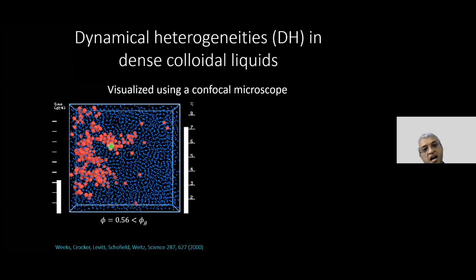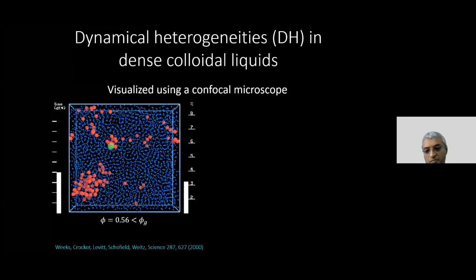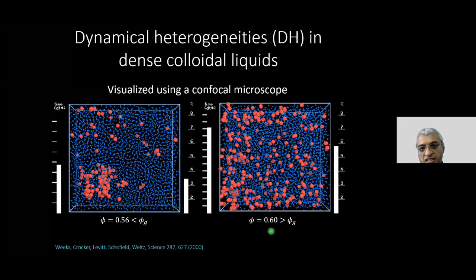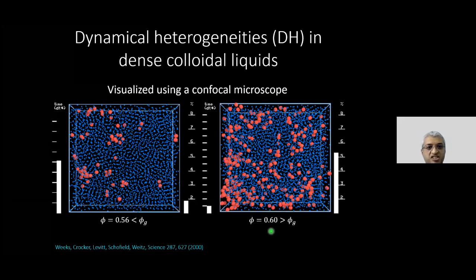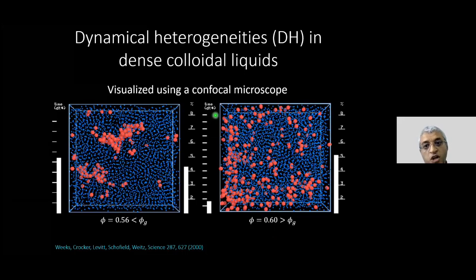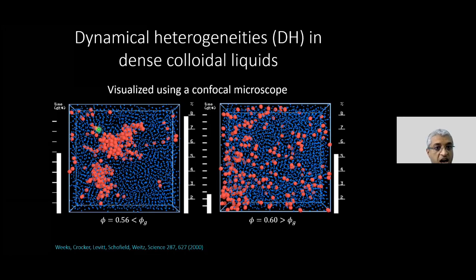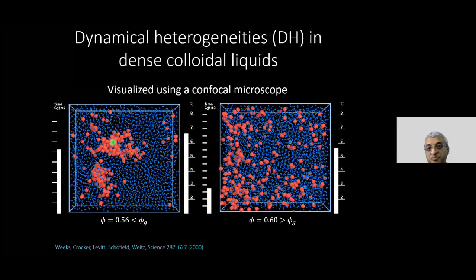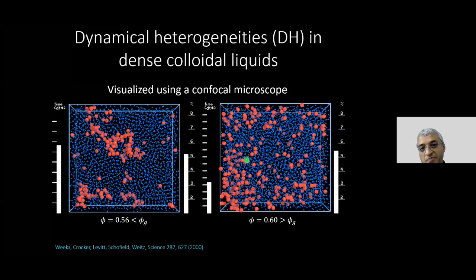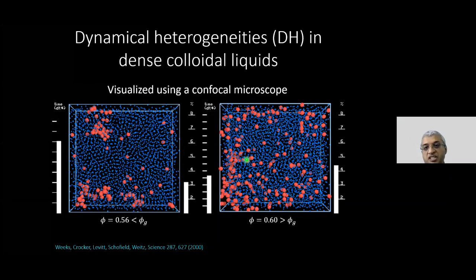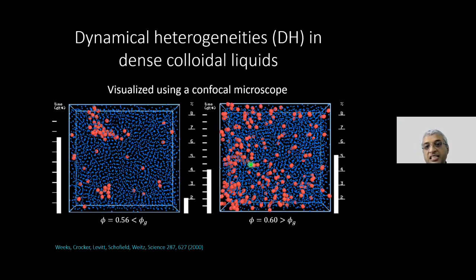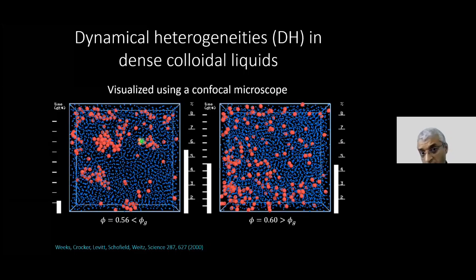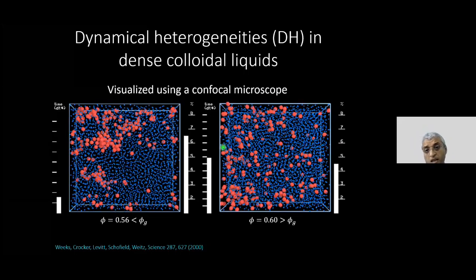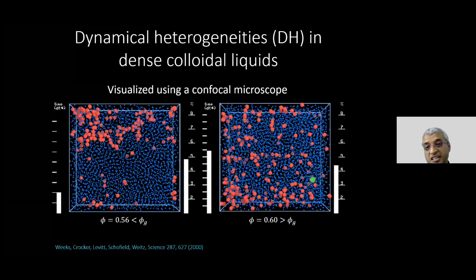Now, in a hard-sphere system, increasing volume fraction is equivalent to cooling temperature. So I'm going to go from phi equal to 0.56 to phi equal to 0.60, which is now past the glass transition. And now you will see in this video that I don't see the sort of large cooperativity that I see here, okay? Because I'm looking at the top 10% of the given system, there'll always be some particles that are mobile, but I see that they are not as large clusters.